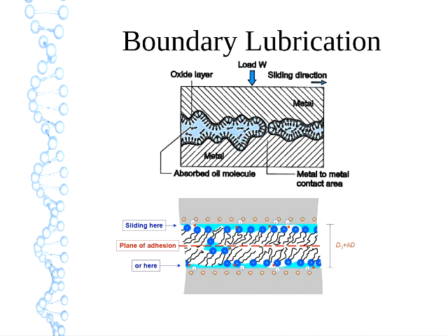Interestingly, even if you don't have lubrication, the top surface will oxidize. So even in unlubricated contact, you do have boundary lubrication to a certain extent. And that is why if you have sliding surfaces inside a vacuum, the friction is usually much higher, because no oxide layer forms on the surface of an unlubricated contact, so the base metals touch even more.